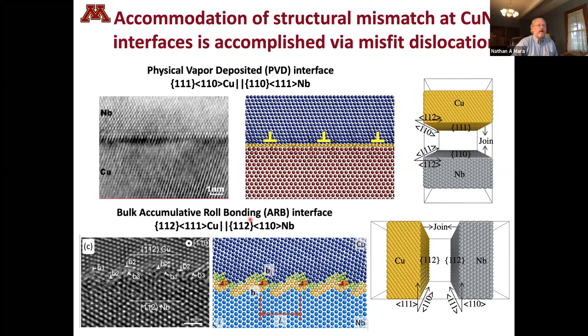Now, different interfaces have different distributions of these kinds of defects. So if we think about copper and niobium again, instead of joining them along their mutual compact planes and directions, we can join them along their 112. And that's what we see in the ARB interface. And this interface is completely different than what we see from the PVD, or physical vapor deposited interface. In the case of ARB, you have this kind of serration between copper and niobium, noted by this dotted line. Here are our 112 planes in both copper and niobium. And when we now look at our distribution of misfit dislocation content at the interface, we've got ones that reside in plane, like this, very similar to PVD. And then we have ones that have an out-of-plane Burgers vector. This completely changes the way that this material deforms. And we'll see that in a moment.